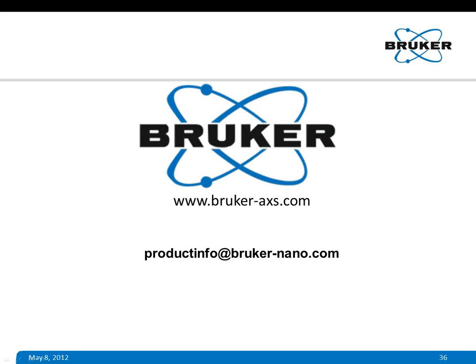Good question. In scratch test, one measurement is not enough. You need to repeat it many times. But if you do progressive load scratch test, probably 3 measurements will be fine to have some kind of reliable number, not statistical, I should say. But if you do constant load scratch test, for getting one critical load, you probably have to perform maybe 10 or 15 or maybe 20 scratches. Then you have to repeat it. So you probably will end up doing 50 scratches, which will be equivalent to 3 scratches under progressive load.